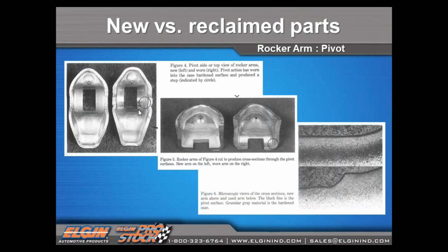Another thing, looking at rockers, again, this is just taking two, a new rocker and one that's out of a used engine, and looking down into the pivot. You can see that there's some indication of wear here. When we section through that, which we did here, you can see the surface that the pivot rides on here is brand new and normal. And here you can see that there's some wear, but it doesn't look like a whole lot of wear. Well, when we mount that, and we polish that and etch it, we can see the surface here,